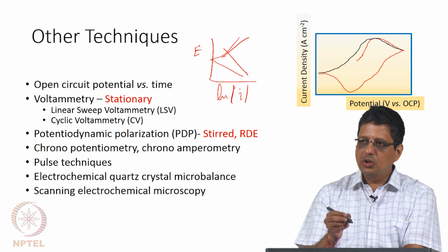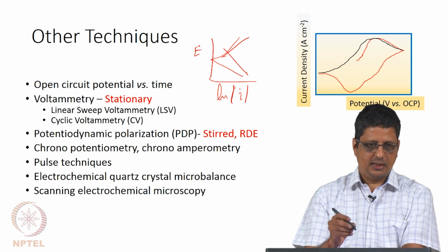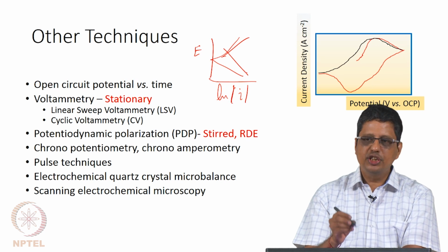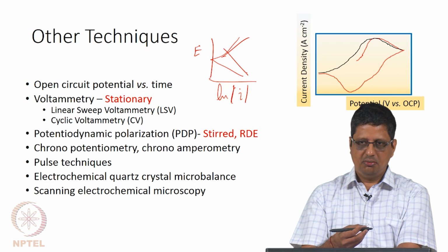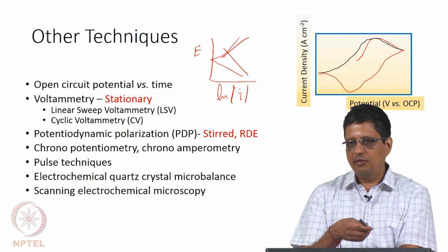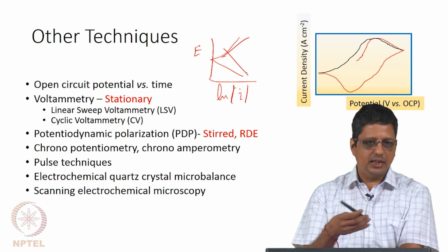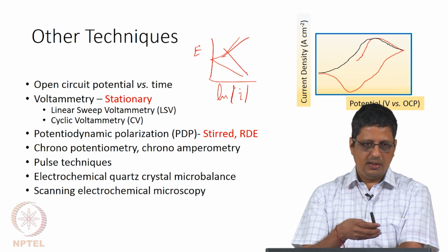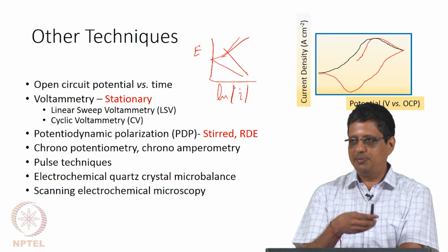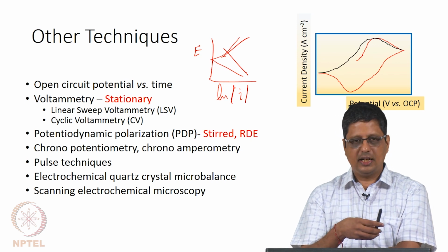That means there is no contribution from the double layer capacitance, and that is correct only when you scan at a low rate. If you scan at a fast rate, software will do this, but the final calculation will not be correct, because the assumption that double layer capacitance does not contribute to this has to be confirmed by us choosing the experimental setup correctly and running it correctly.